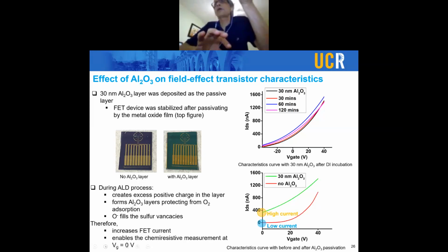As well, the aluminum oxide also is a good way of immobilizing biological molecules using the chemistry of simple silanization. So you can silanize the aluminum oxide to create molecules that can then be linked to the antibodies. And also the aluminum oxide provided some benefit of a significantly higher current at the zero gate potential, which allowed us to then do the measurement in the true chemiresistive mode as opposed to FET mode. Because we like to work with chemiresistive, we don't want to sweep gate potentials. So that's why this was what we decided to do.